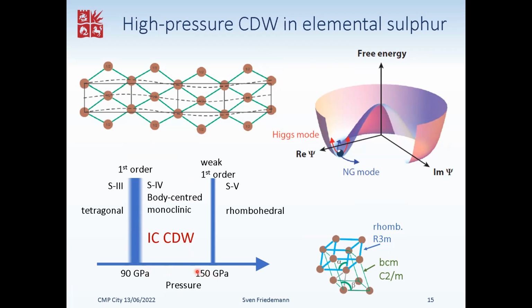This has been previously already observed in X-ray diffraction. It's incommensurate with a Q vector close to 3/4, and at the same time, this phase's underlying structure is also a monoclinic structure, which is a distortion of the high pressure rhombohedral structure of sulfur. And what we could show with our Raman measurements together with ab initio calculations is it's no coincidence that it is both a charge density wave and a monoclinic distortion, but they actually stabilize each other. But let me first show you the results.